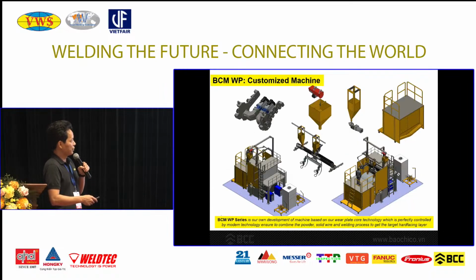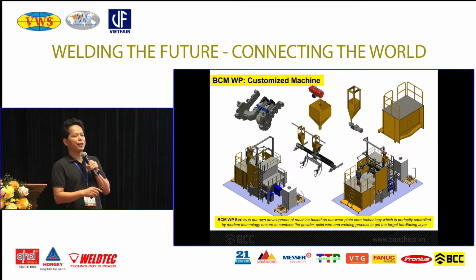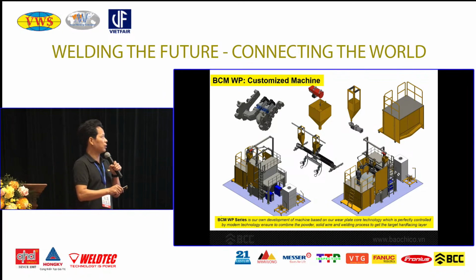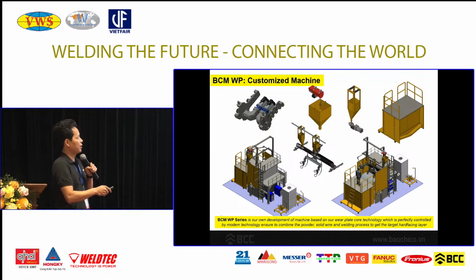So as I mentioned, the system is very important, how to control it. It had to control the acceleration, the movement, or the track movement of the welding, the traveling speeds, the oscillating, the range of oscillation and the points in between, all the traveling. And very important, as I mentioned, we had to control how much powder we feed into the welding to make sure that we control the thickness of the welding layers we deposit on the surface.